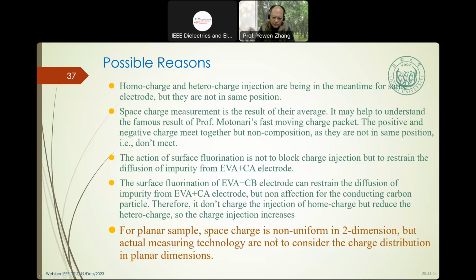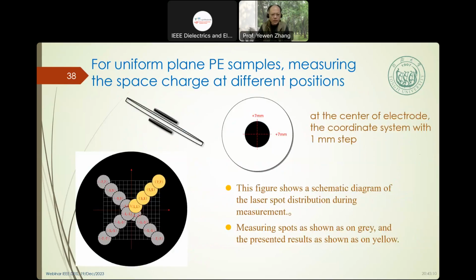For the planar sample, space charge is not uniform in two dimensions. But the PEA measurement does not consider the charge distribution in the planar dimension. We measure only this side, but don't consider the other dimension. So we give some experiments. For the uniform plane PE sample, we measured space charge at different positions, with a coordinate step of 1 millimeter. We measure this one and this one. The measuring spots are shown in gray and the presented results are shown in yellow. We measured many, but show just this one.